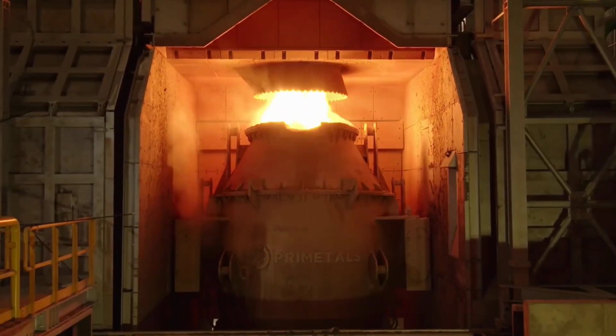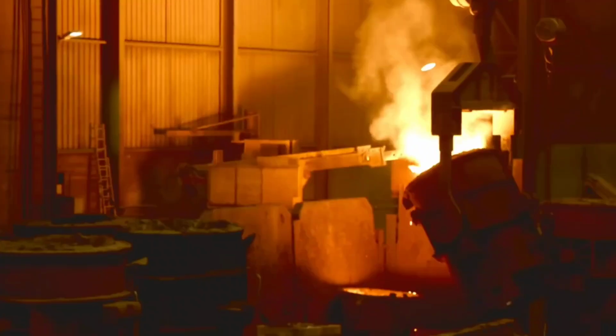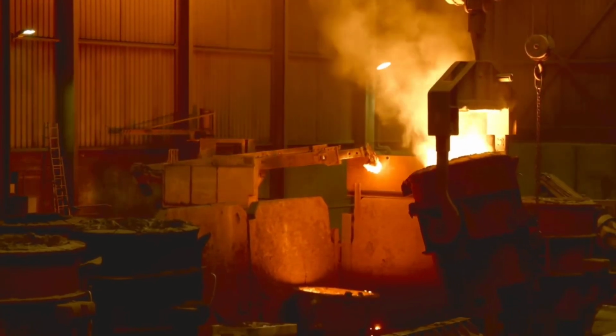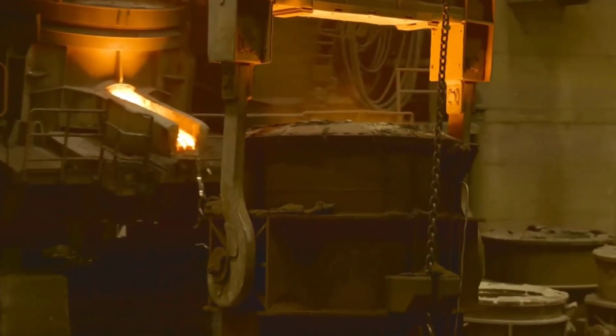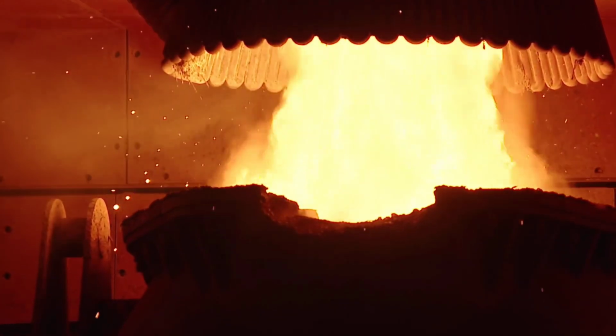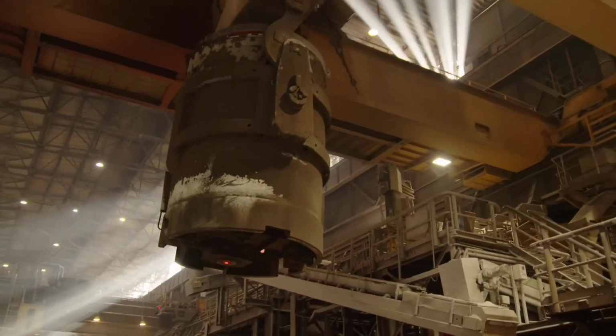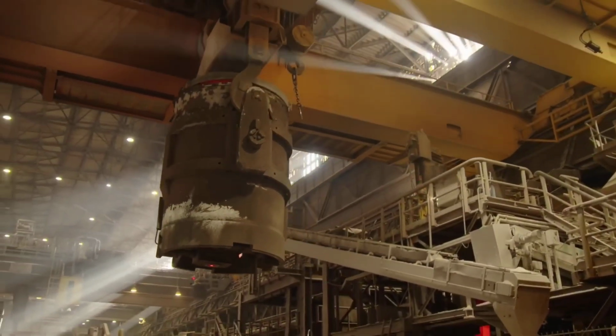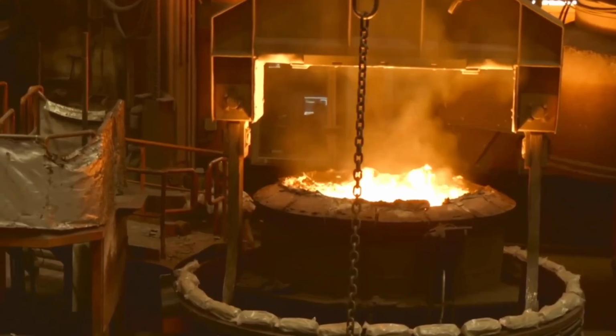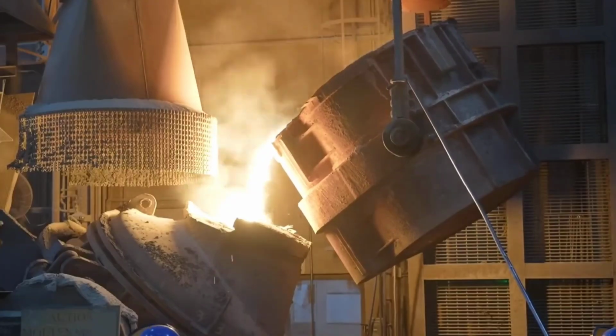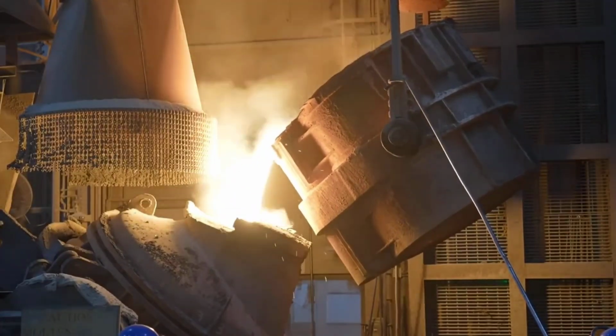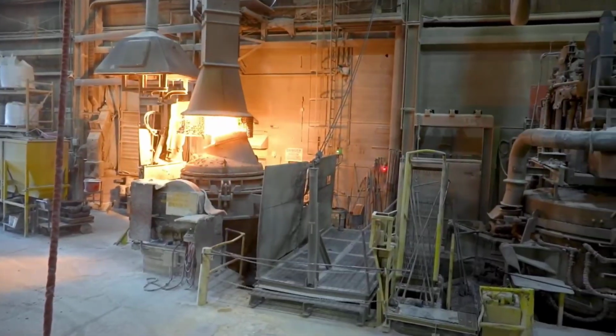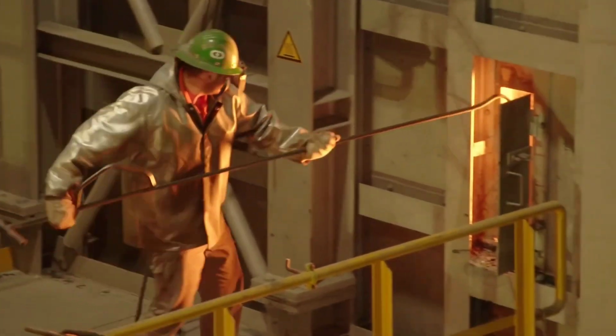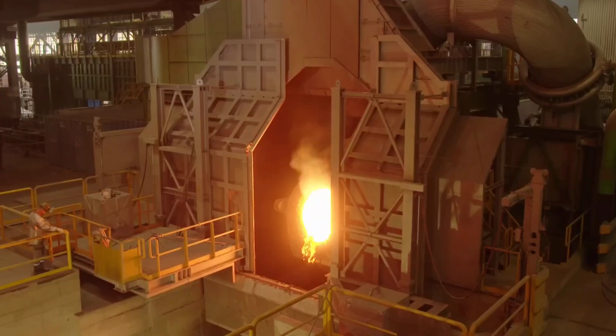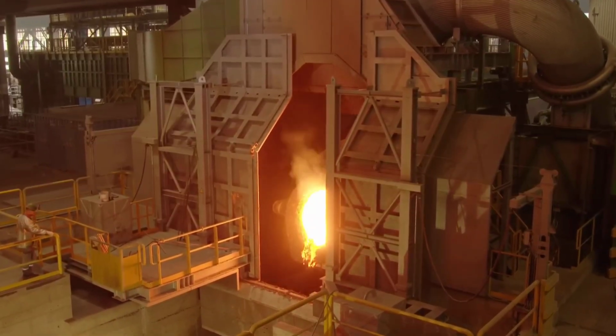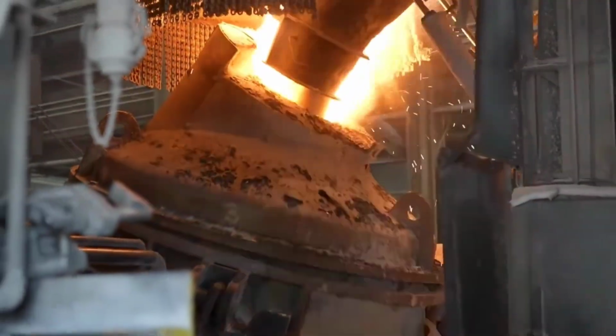After leaving the flotation system, the silver-rich froth is collected, thickened into a dense slurry, and transferred to the preliminary smelting stage, where fire and metal begin to interact. The entire batch is fed into a specialized furnace operating at temperatures above 1000 degrees Celsius. The furnace, shaped like a rounded crucible, is lined with high-temperature refractory materials capable of withstanding sudden fluctuations in heat and pressure. Once the lid is sealed, the mixture undergoes purification by fire.